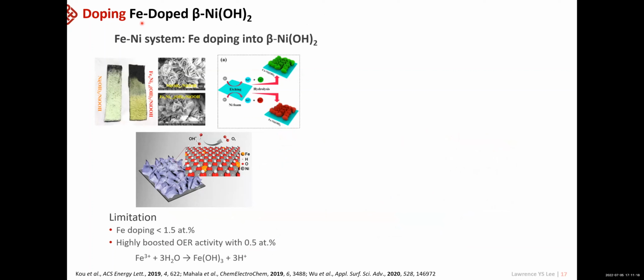We worked on beta nickel hydroxide species, quite similar to the LDH. The reason why we chose this is it's known that when you dope iron species into the nickel system, their OER property increases a lot. And we understood it because these two atoms are located on opposite sides of the volcano plot, so they can work with each other to optimize the bond strength of the intermediate species. Also, when you insert iron into the nickel species, their conductivity could be increased significantly. And we expect that there will be some partial electron transfer between iron and nickel species so that the active species can be more easily produced.